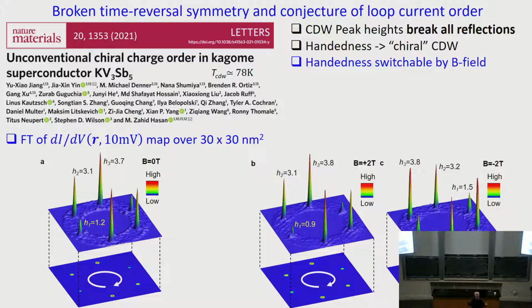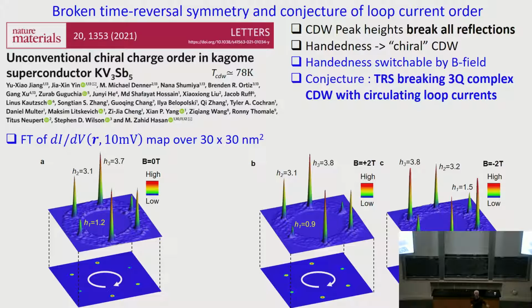And you have no magnetism. What can you say about what happened that broke time reversal symmetry? So we conjectured, in the absence of magnetism, maybe the CDW state has a very exotic ordering, that is the current. There is persistent current that orders in the CDW state. Right? So it's circulating loop current order. So that was a proposal, and many people tried to repeat this experiment.